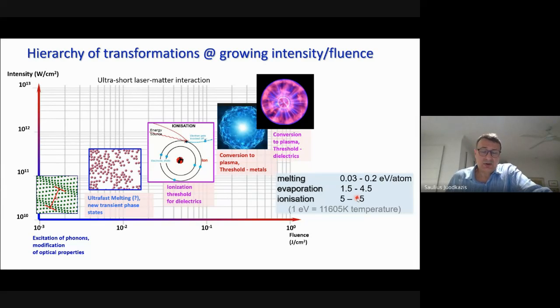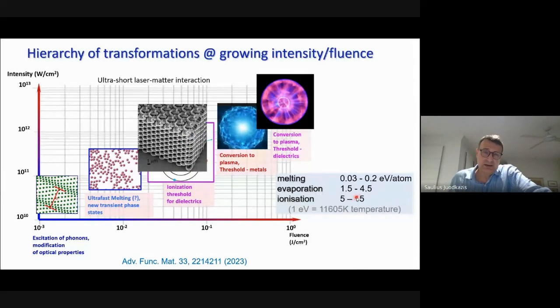And usually we are not reaching self-focusing in many cases. So really we have direct writing. We deliver energy exactly to the point. And this is separate story, but I want to show that all those 3D polymerized structures, which we see many times these days, they are actually fabricated at intensities which are quite high. They are almost half of the breakdown intensity when you make ionization of your polymer. You are writing those structures at 1 terawatt per square centimeter. So these are really intensities when we are delivering energy by bond breaking, by creating free radicals directly by light. We don't really rely on photoinitiators. We can use them, but if we don't use them, we are still able to do 3D fabrication, but this is a little bit different story.